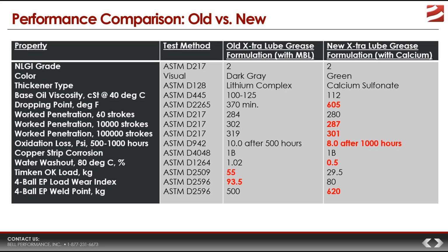The basic rule of thumb when interpreting results is that the higher the number on the work penetration test, the thinner the grease is. This is because the work penetration test is the same one used for cone penetration, which gauges the NLGI grade. They take a weighted cone and drop it into a vat of grease to see how far down it sinks. A thicker grease won't drop down as much, while a thinner grease will penetrate more. That's why a higher score means a thinner grease.